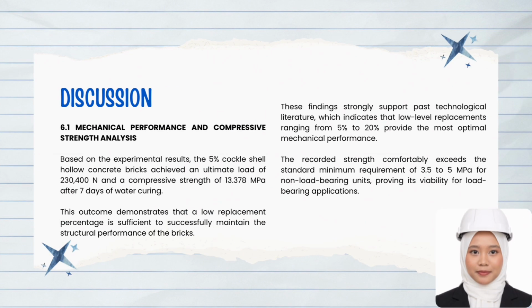For mechanical performance, after a 7-day curing period, our bricks achieved an ultimate load of 230,400 newtons and a compressive strength of 13.378 megapascal. This outcome demonstrates that a low replacement percentage is sufficient to successfully maintain the structural performance of the bricks. These findings strongly support past technological literature, which indicates that low-level replacement ranging from 5% to 20% provides the most optimal mechanical performance. This high strength comfortably surpasses the standard 3.5 to 5 megapascal required for non-load bearing units.